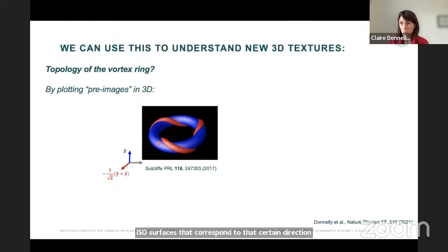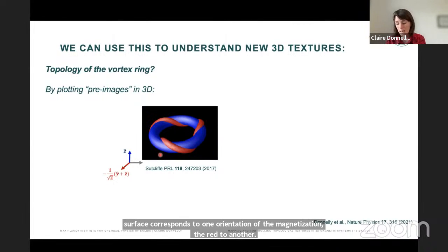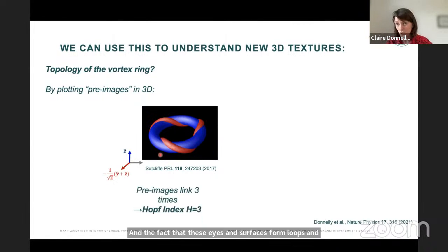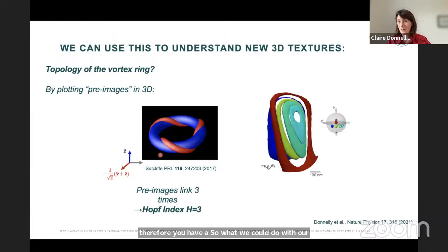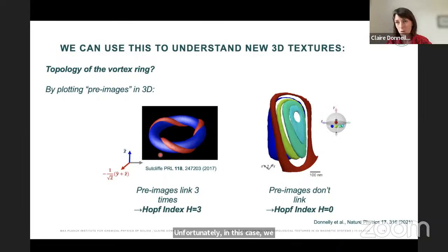So you see here this image taken from the work of Paul Sutcliffe on Hopfions. The blue isosurface corresponds to one orientation of the magnetization, the red to another. And the fact that these isosurfaces form loops and interlink means that you have a non-zero Hopf index, and therefore you have a Hopfion. So what we could do with our data was do the same thing for our vortex rings. Unfortunately, in this case, we were able to determine that these pre-images do not link, and therefore we do not have a Hopfion.